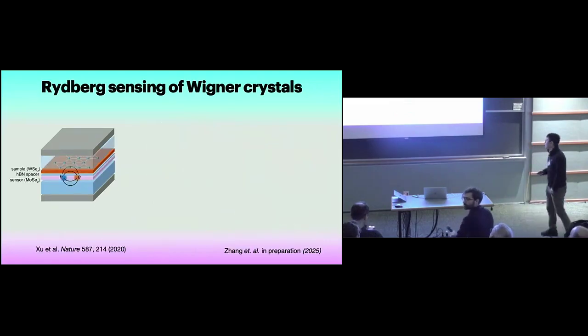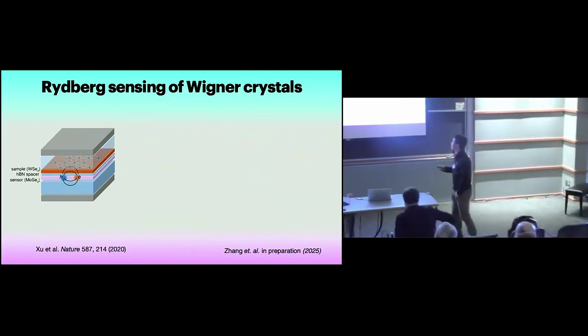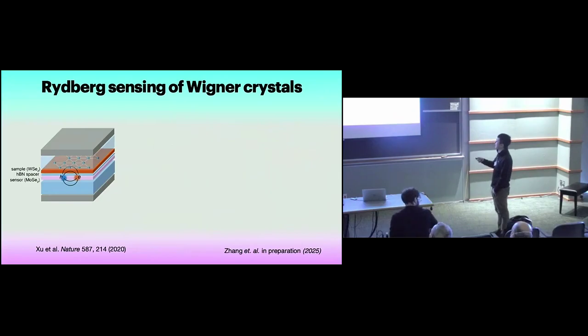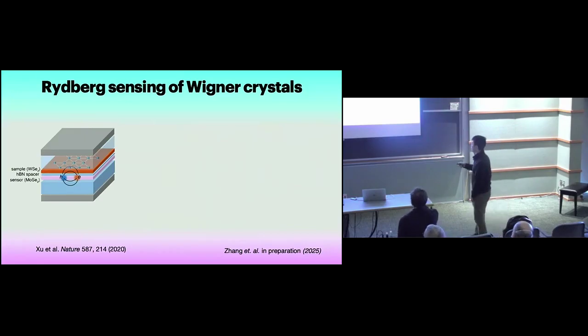Okay. So another thing we can do is to look at the dielectric response of the Wigner crystal. So instead of just using the exciton in this same layer as a probe, what we can do is to put another layer in here, in this case MoSe2, and use the exciton in a different layer to sense the Wigner crystal, right? So as we might expect, if you have a Wigner crystal versus electron liquid, the screening of this layer will have different effect on the exciton energy in this MoSe2 layer. This was a technique developed by Kin Fai's group, so-called Rydberg sensing. You want to use the Rydberg states of the exciton because they have large Bohr radius, so you can penetrate deeper or further from your sensing layer.